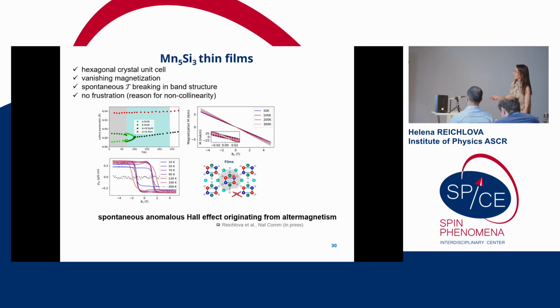And we see that the thing which in the bulk is the T-t symmetry is not a symmetry in the thin films, because here again we can do the exercise to flip the magnetic color, let's say the red to the blue, and then we see that we cannot do any translation operation to recover the original image. So again, the T-t symmetry is broken here, which fulfills the altermagnetic criteria by a slightly different mechanism, right? Because here no rotation is involved, and therefore it's a strong hint that our spontaneous anomalous Hall effect indeed originates from the altermagnetism.